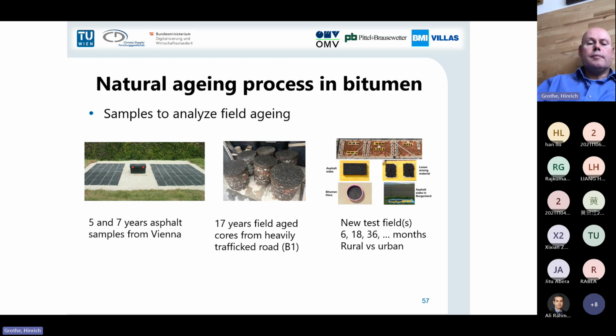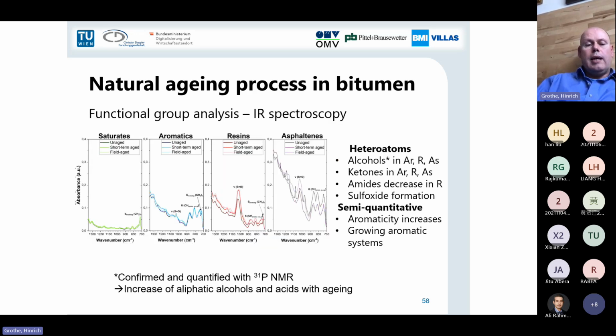And then we had samples from a road, it's near Enns, and the samples are 17 years old. And then we were also producing short-term aged samples in a way that we just placed bitumen samples on the roof of our building. And again, we can run infrared spectroscopy, and we can run that infrared spectroscopy on all 4 different fractions, on saturates, aromatics, resins, and asphaltenes, and observe the differences in different windows.